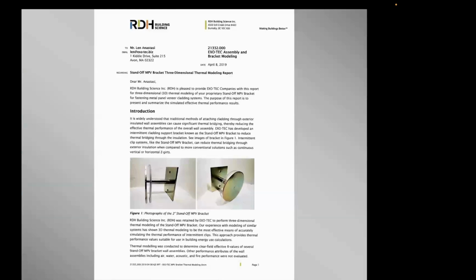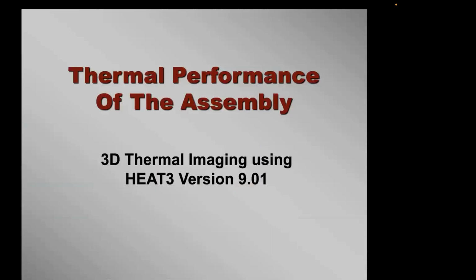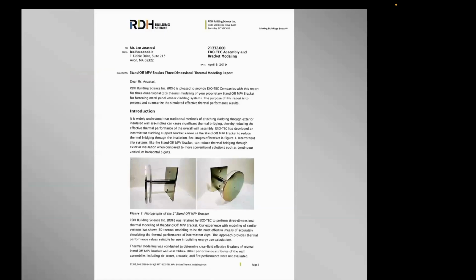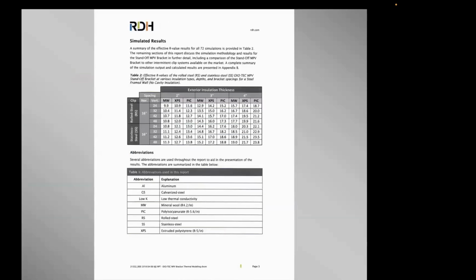So I did hire RDH to do 3D thermal modeling for that using Heat 3 version 9.0. Here's the report. They ran the thermal modeling, and they show you this table of that assembly, depending on your stud spacing, and they want 24, 32, 42, and 48. I said, why? Mine are 16 by 48. They said they wanted to compare it with the other systems. So I don't think these values are really needed. And then they go 2-inch mineral wool, extruded polystyrene, polyiso, 3-inch, 4-inch.